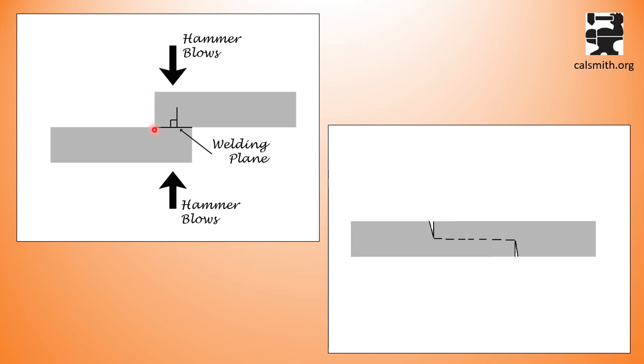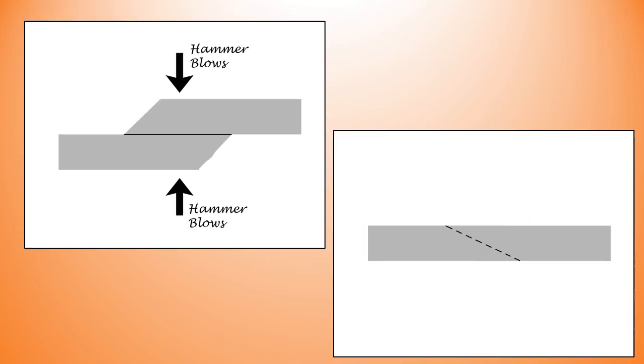To me, these sharp ends look like a chisel, and indeed that's exactly how they act. They will push down into the metal, creating a crack that you cannot blend in. So to get ahead of that, you simply create a slope that is more in line with the welding plane. And that's why I always say perpendicular-ish to the welding plane. You want this to blend in nicely, and with this configuration, that's exactly what will happen.